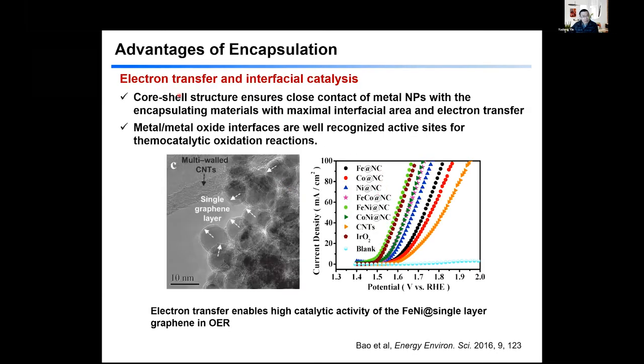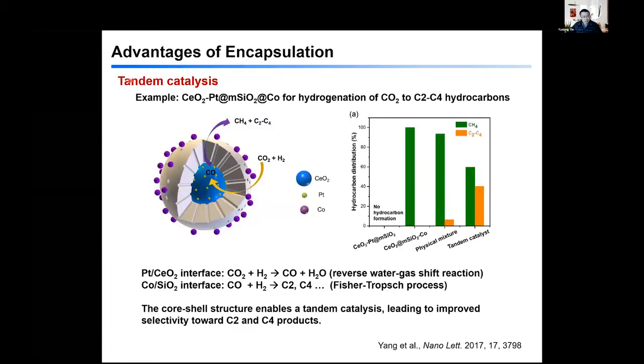Okay, and there's also enhanced electron transfer, because you wrap these particles. For example, in this case, we wrap them with a monolayer of carbon, and when they get in touch with the support, in this case carbon nanotube, the electron transfer is excellent, and then we can have very good performance in, for example, the OER reaction. Okay, and there are also opportunities for organizing tandem catalysis. You have one type of nanoparticles inside, and then you have these mesoporous channels. And then you have another catalyst outside, and you can do sequential reactions, and then you can enhance the selectivity, for example, in this carbon dioxide to C2 and C4 hydrocarbon.